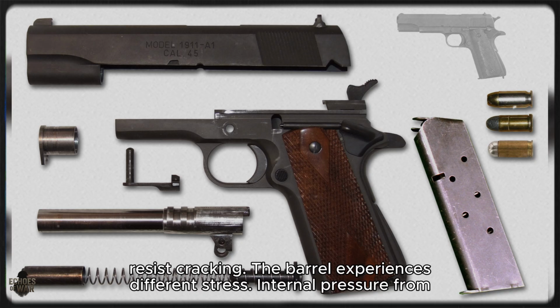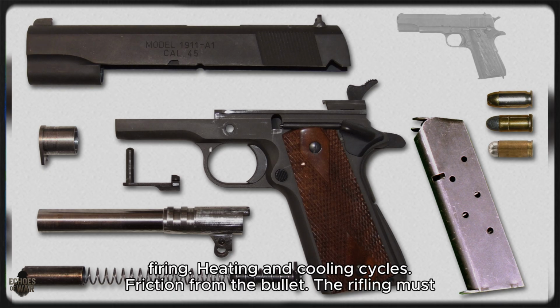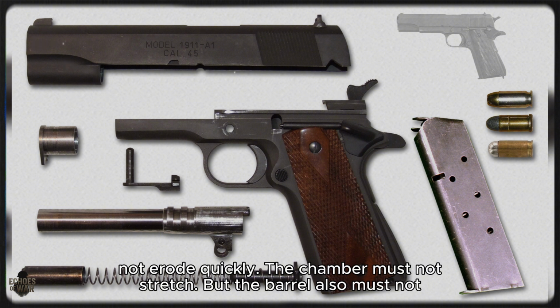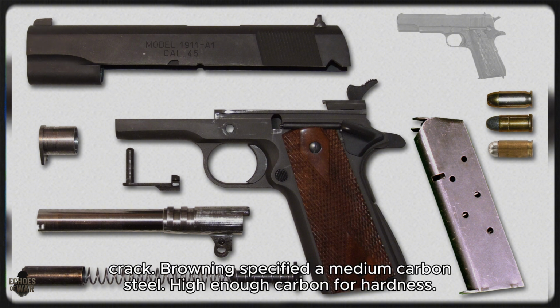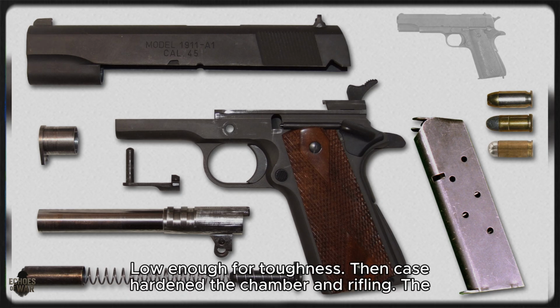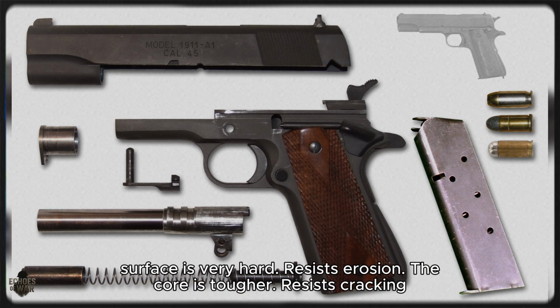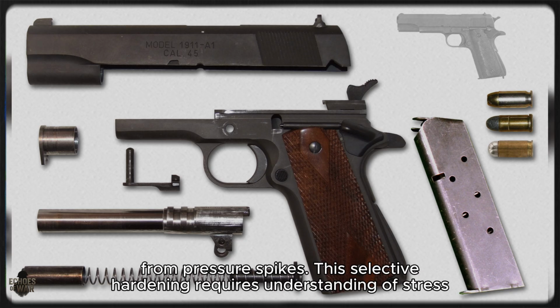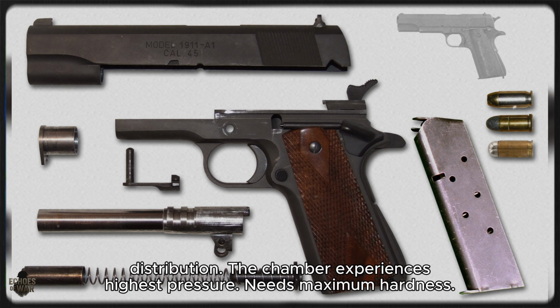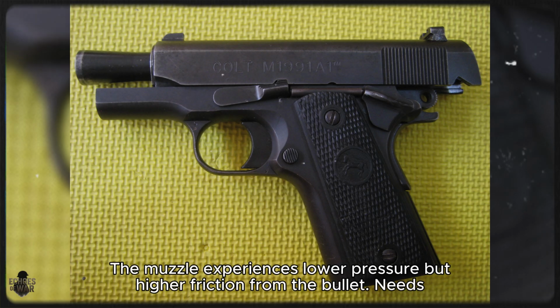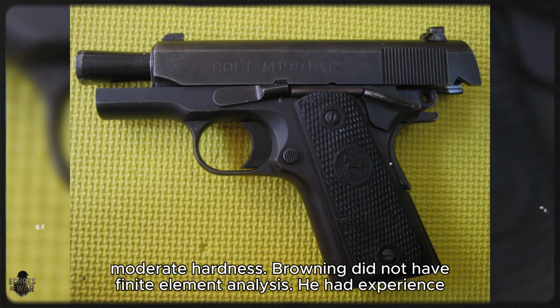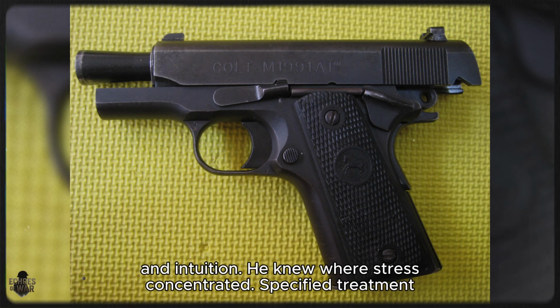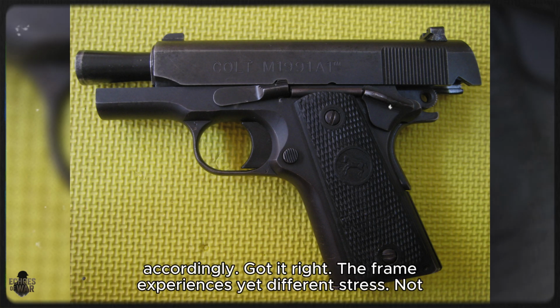The barrel experiences different stress, internal pressure from firing, heating and cooling cycles, friction from the bullet. The rifling must not erode quickly. The chamber must not stretch, but the barrel also must not crack. Browning specified a medium carbon steel, high enough carbon for hardness, low enough for toughness, then case hardened the chamber and rifling. The surface is very hard, resists erosion. The core is tougher, resists cracking from pressure spikes. This selective hardening requires understanding of stress distribution. The chamber experiences highest pressure, needs maximum hardness. The muzzle experiences lower pressure but higher friction from the bullet, needs moderate hardness. Browning did not have finite element analysis. He had experience and intuition. He knew where stress concentrated, specified treatment accordingly, got it right.